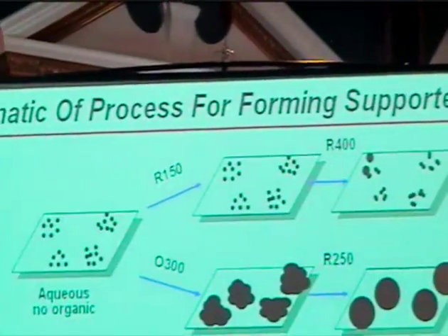And if you can see here, there are small ruthenium crystallites located in these circles, but they're highly clustered in regions that we like to call little graveyards. And so when you go ahead and you actually take these same areas and reduce them at 400 C, you actually can see the much larger particles where those little graveyards have now, the particles have clustered into much larger ruthenium. So this nanoscale distribution has created a significant difference between the two materials.